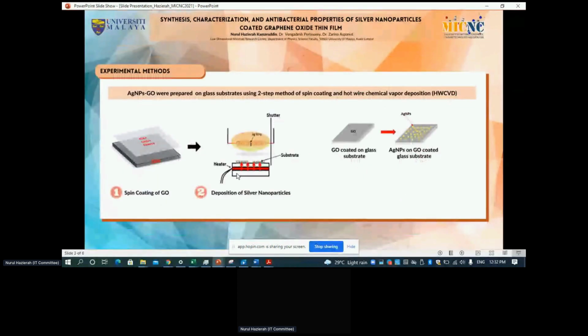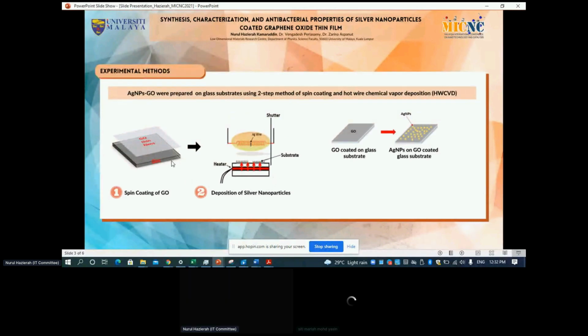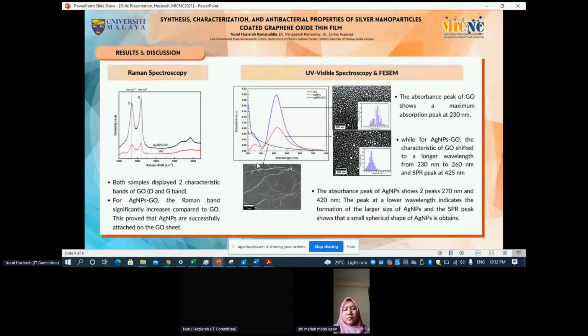And for the deposition of graphene oxide thin film, firstly, we synthesize the graphene oxide using a standard simplified Hummers method. After we obtain the graphene oxide suspension, we spin coated the graphene oxide onto the thin films. And then this graphene oxide thin film will proceed to the next step using hot wire CVD. This graphene oxide thin film was used as a substrate for the deposition of the silver nanoparticles. And the samples were then characterized to confirm the formation of silver nanoparticles and graphene oxide.